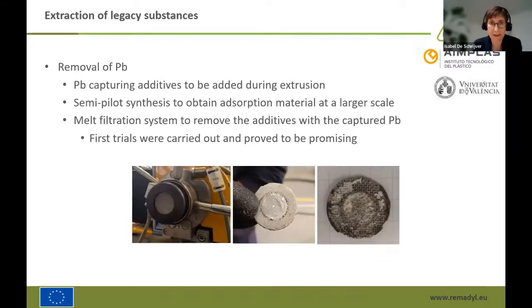A second option, which is being evaluated by our partners AIMPLAS and University of Valencia, is, instead of using solvents to remove the lead, to use a new kind of melt filtration, where we work with a complexing agent that will bind the lead present in the PVC, and where we use the filter technique to filter out the lead from the PVC matrix. The first trials were carried out, and they are very promising to use a classical melt filtration on an extrusion line to filter out the lead and to complex the lead on that filter material.